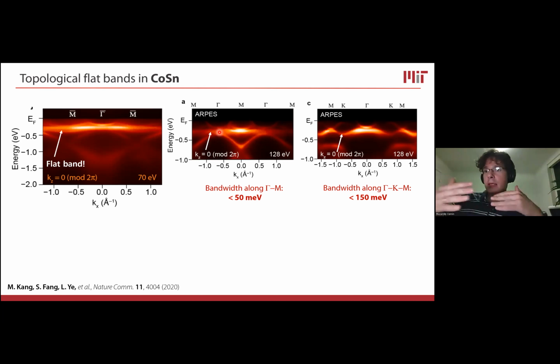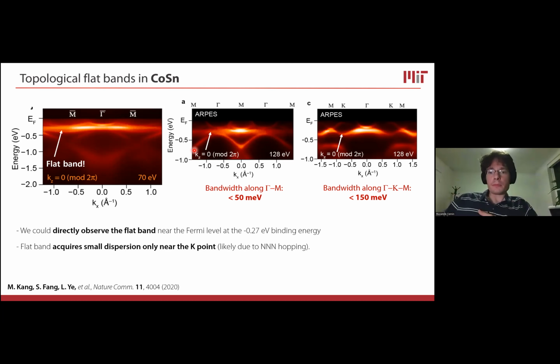So these are the flat bands that are associated to the same set of bands that arise from the same orbitals that give us the Dirac bands. And we find them at a binding energy of about 270 milli-electron volts, so not terribly far away from the Fermi energy, possibly within range of doping by gating, if a single Kagome layer could be isolated and you could construct very similar devices, field effect devices, to what you can do with graphene. And it acquires this small dispersion only near the K point, again, due to the longer range hopping.